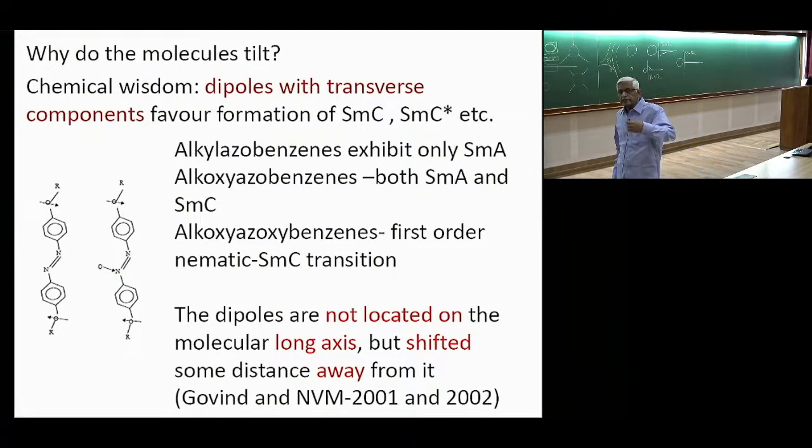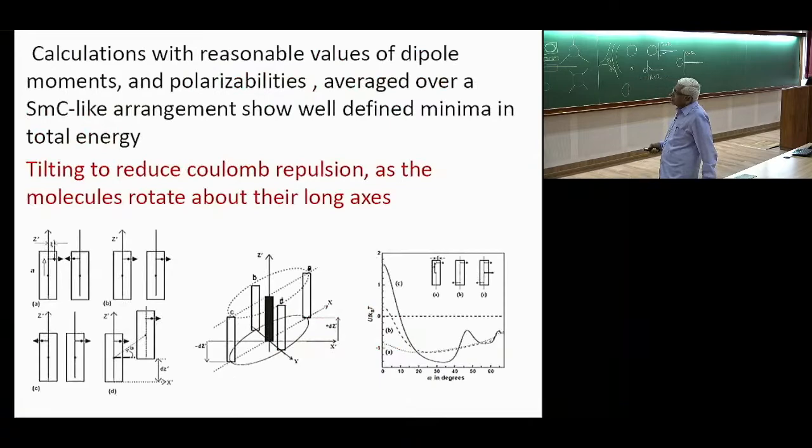So it's clear that lateral dipole moments are necessary. McMillan had used a dipole moment, but he used it in the center of a rod. If the rod rotates freely, then the dipolar interaction is averaged out. So what he said was they don't rotate freely to get the tilting. But then NMR experiments and then neutron scattering showed that the rotation is not completely free, but certainly not hindered to the extent that he required for the formation of Smectic C. So that theory was out.